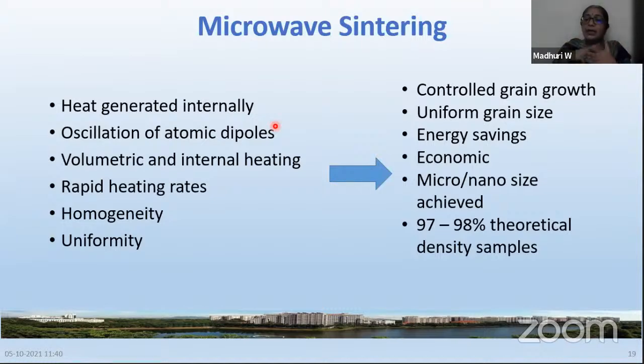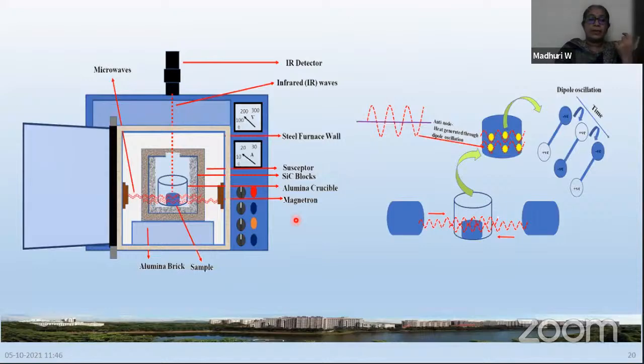You're having a dense ceramic. The density can be as close as 98% of the theoretical density. And you can even control the particle size. If you want it to be in nano, you can play with the inputs of your microwave sintering programming and keep your materials in nano. If the starting materials are nano, you can still keep them in the nano scale, or if you want to grow them to micro scale, you can do that, depending on your sintering programs. Fine. So these are the advantages of microwave sintering, and this is what is hybrid microwave sintering.